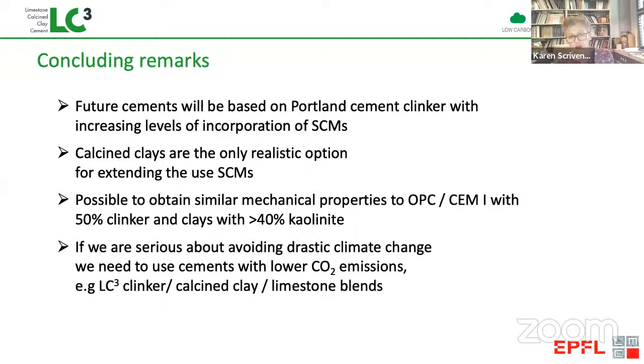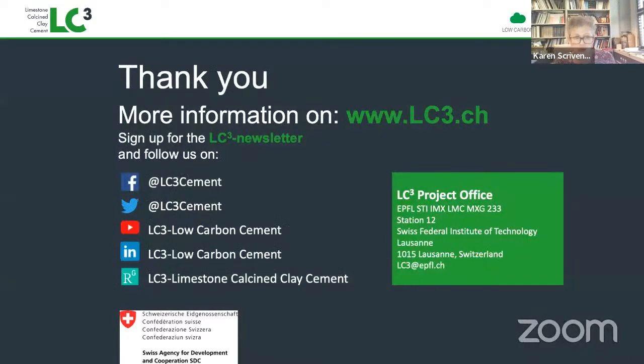So just to conclude, I hope I've managed to convince you that this is really the future of cements. You know, we don't really have any viable alternatives. We can produce on the same scale as Portland cement, but we can substitute with SCMs. And in terms of SCMs, calcined clays are really the thing we have that can take the substitution levels to higher amounts. And to get similar properties even to OPC, we can do this with only 50% clinker and clays with only 40% kaolinite. So I think this is a very important technology if we're serious about reducing CO2.